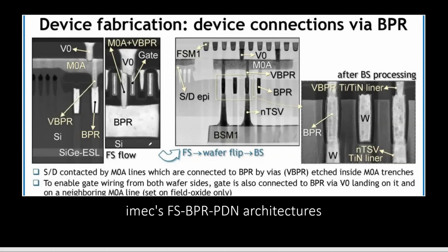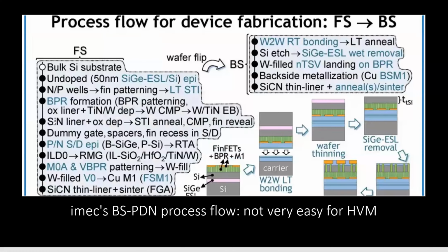They need to dig holes, right? And then they need to stop, because digging through silicon, you have to find another idea. So SiGe is the one they used, and there is a reason behind it, because that's how you can do epi. So this is for the more complex one, the front side to the back side.